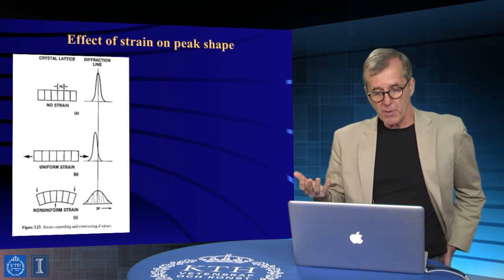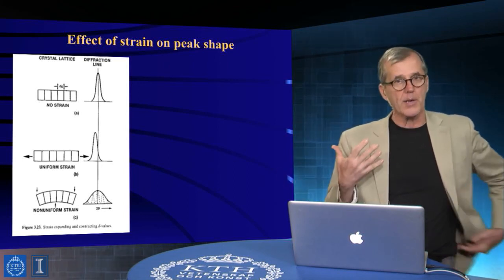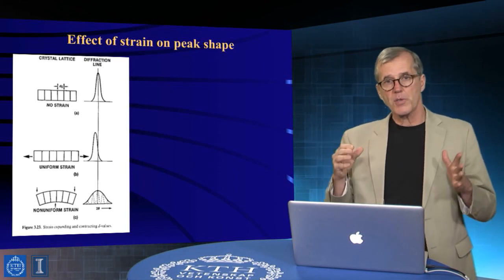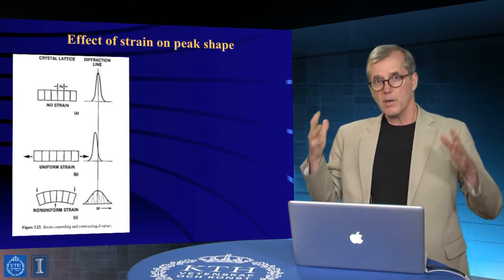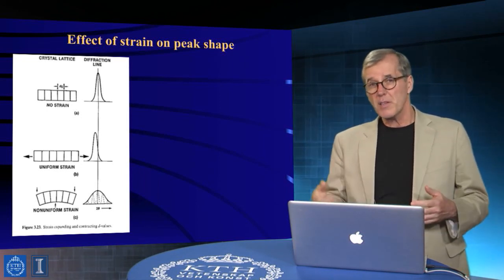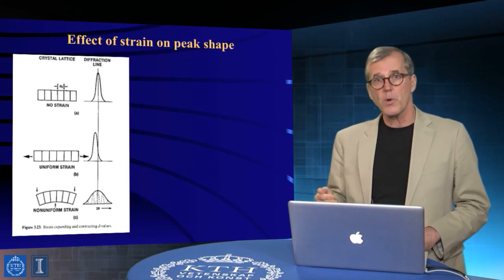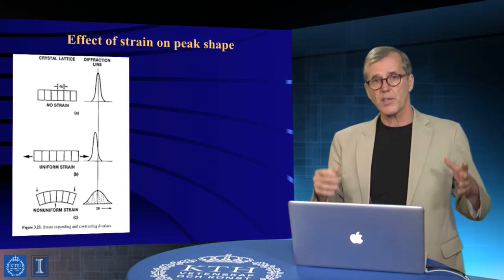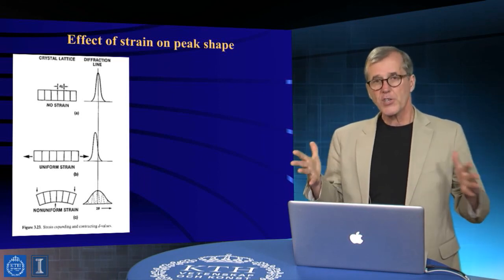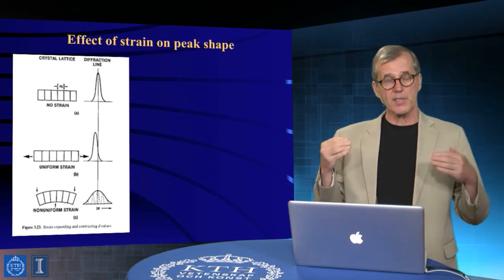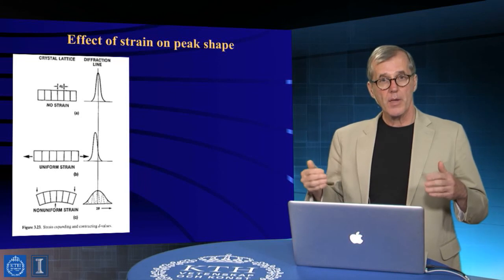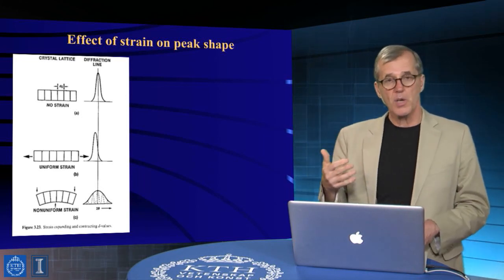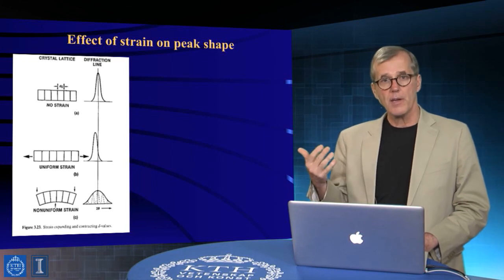Now, we mentioned strain, right, in these deviations. So, strain is an important thing, and it can come substitutionally, but it can come from other sources as well. And actually, in some systems, strains are very important because they underpin how materials not only will function, but also can really fundamentally modify, and I mean modify in profound ways, underlying chemical properties. So it's not just a consequence for mechanics, it's a consequence for everything. So for example, in semiconductors, strain actually changes the energetic characteristics of the material, like in the sense of how electrons and holes propagate in the material. So, strained semiconductors can be used to make transistors, which have massively modified transport properties.